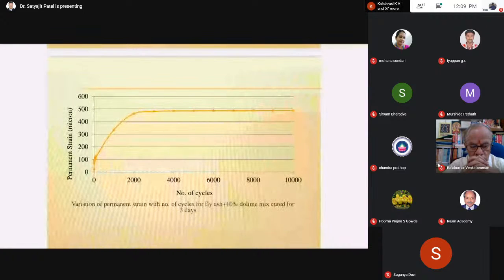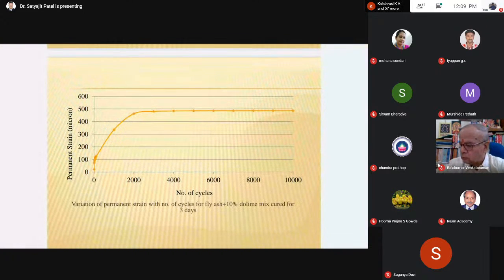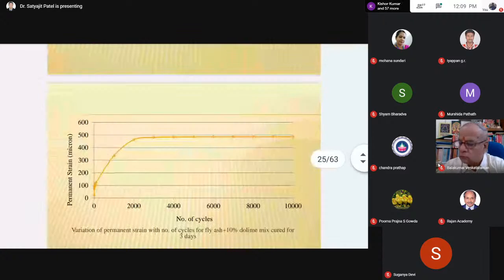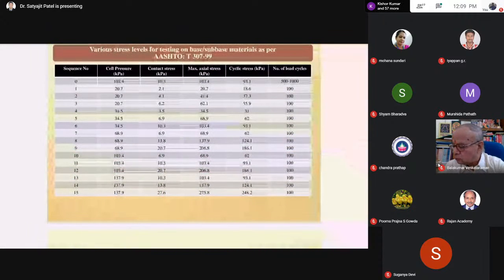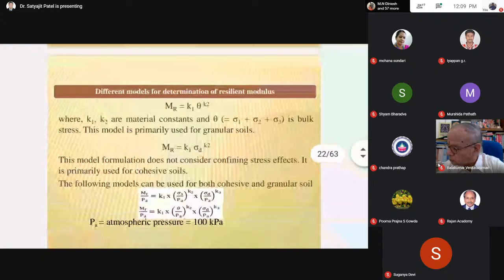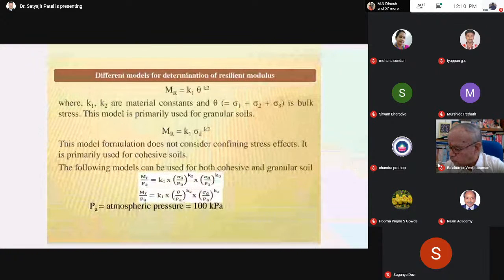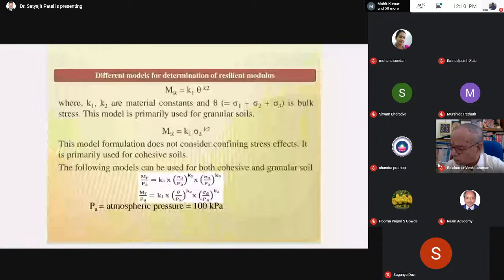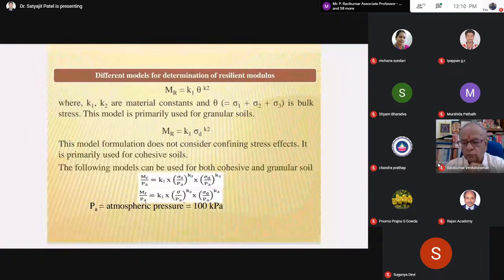After the permanent strain gets stabilized, up to that point you have to apply the cyclic load in the conditioning phase. Then from this test we will obtain 15 different MR values for 15 different stress combinations. From these, we can find the material constants K1, K2, K3. If you correlate the MR value with bulk stress theta, where bulk stress is sigma 1 plus sigma 2 plus sigma 3, then you have 15 different combinations of MR and theta. So you will get the K1, K2 values from these correlations.